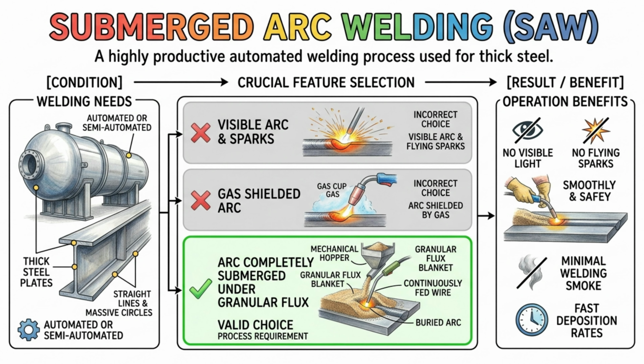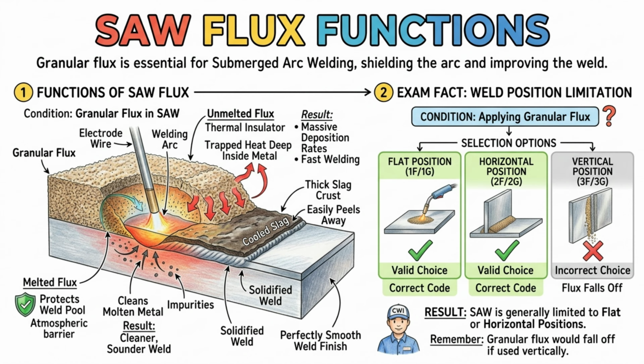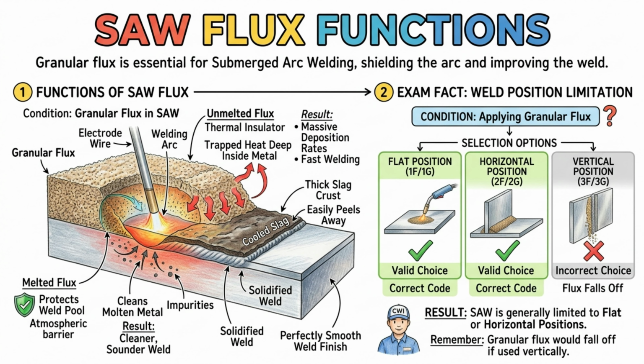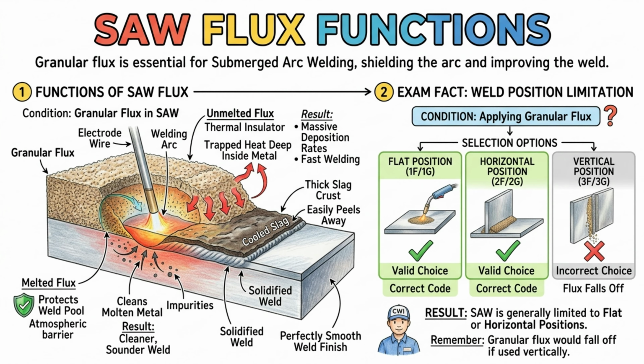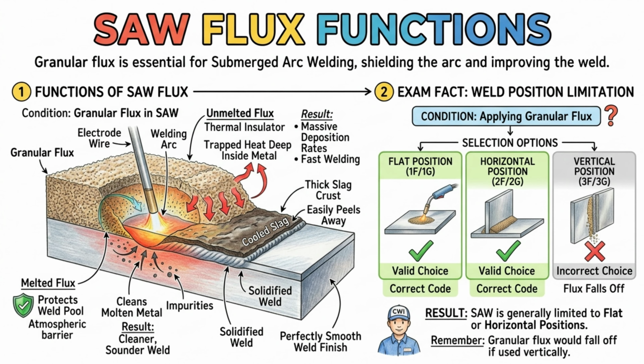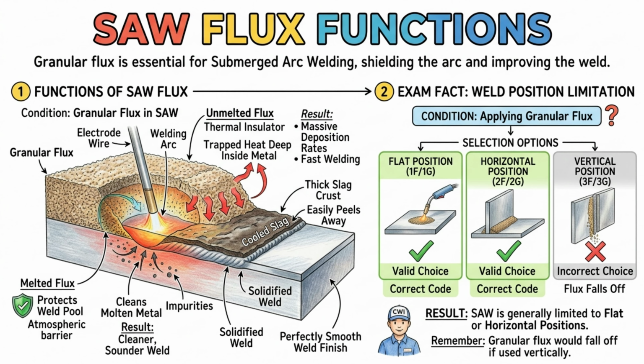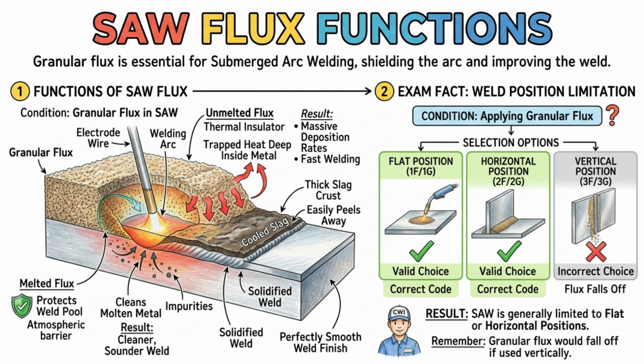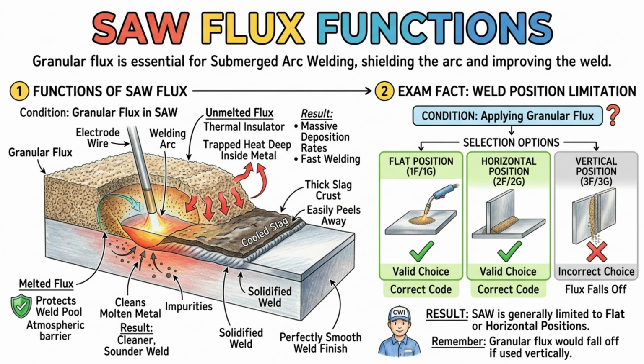The granular flux in submerged arc welding performs multiple vital functions. The flux immediately surrounding the arc melts into a liquid, protecting the weld pool and cleaning the molten metal of impurities. The unmelted flux on top acts as an incredible thermal insulator, trapping the heat deep inside the metal and allowing for massive deposition rates. After the machine passes, the molten flux cools into a thick slag crust that easily peels away to reveal a perfectly smooth weld. In your exam, remember that submerged arc welding is generally limited to flat or horizontal positions because the granular flux would simply fall off if used vertically.